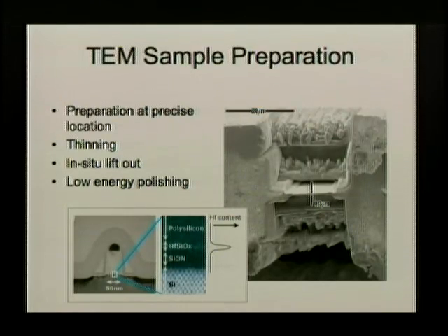Basically, that would be the first stage that allows you to image this whole thing in a scanning electron microscope. If you're interested in more detail, if you want to see structures much smaller than, let's say, 10 nanometer, you would possibly like to use a transmission electron microscope. This also has something to do with one of the first slides I showed, where you see that the signal the electron beam generates does not come directly from the surface of the sample, but the beam goes into the sample several tens of nanometer. So you actually average over a very large area.